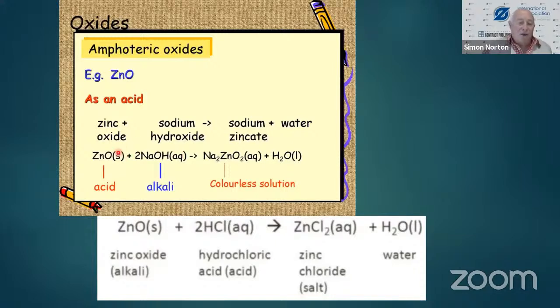Now you know from your early school chemistry that an acid and a base gives you a salt plus water. So here you have an acid, zinc oxide, and a base, sodium hydroxide. It forms sodium zincate, which is a salt, and water. So in this role, zinc oxide, which forms immediately when zinc is exposed to the oxygen in the atmosphere, is acting as an acid. But equally, zinc oxide can also operate as a base. So in this particular case, zinc oxide is an alkali reacting with hydrochloric acid in aqueous solution, which is an acid, to form a salt, zinc chloride, and water.